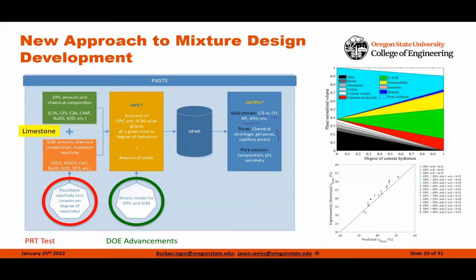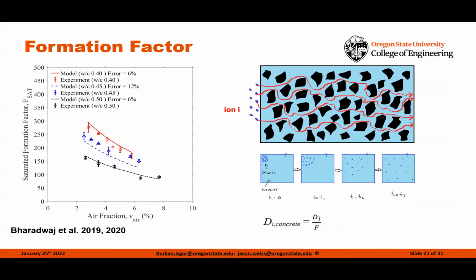But in addition, we can also start predicting things like the pore solution, which is going to be important for things like ASR reactivity, the pH of the system. It's going to be important for interpreting electrical resistivity measurements. So we have the ability now to predict these things simply by knowing the initial chemistries of the overall systems that we're looking at.